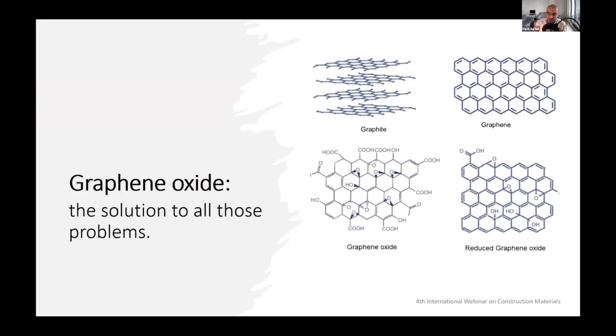Then, in contrary, however, it is not hydrophobic, and I mean graphene oxide. Rather, it is hydrophilic, actually, because of the oxygen atoms, which means that it not only doesn't create chunks of little black balls, it actually helps in a better dispersion. That continuous path for electrical and thermal conductivity can be achieved by using graphene oxide instead of graphene in concrete.